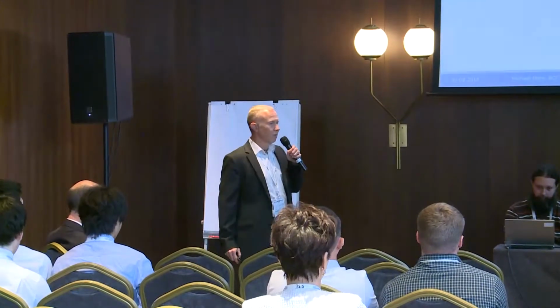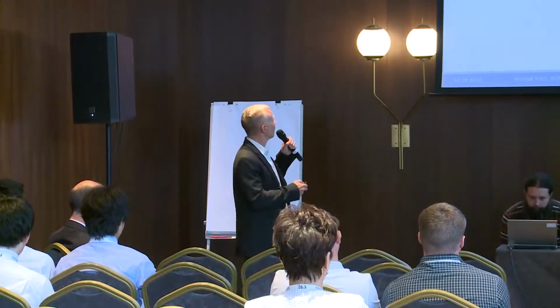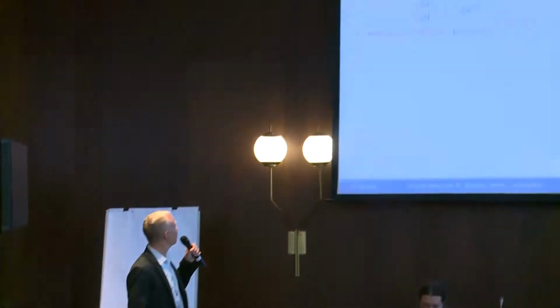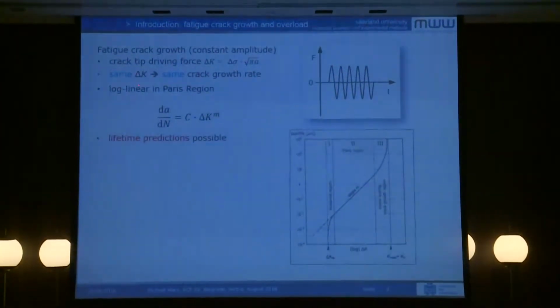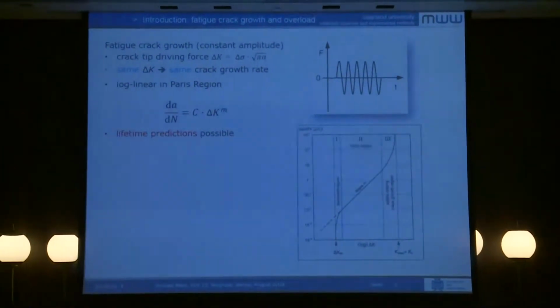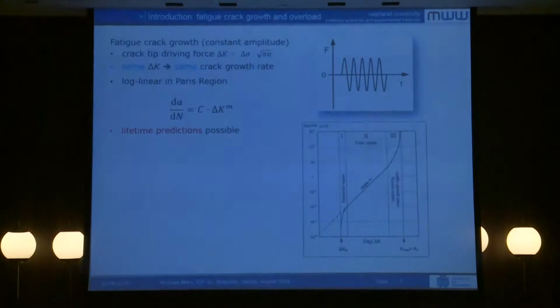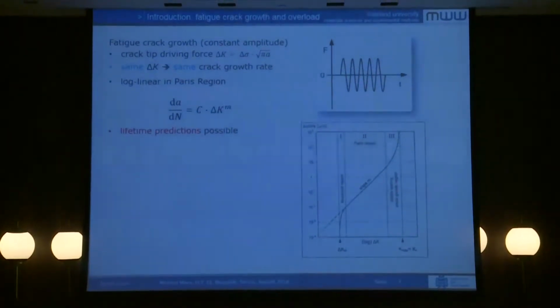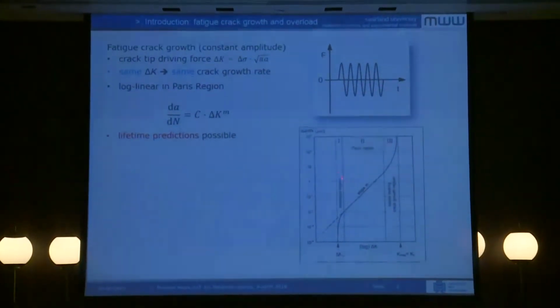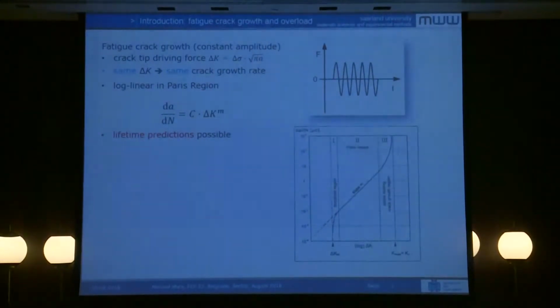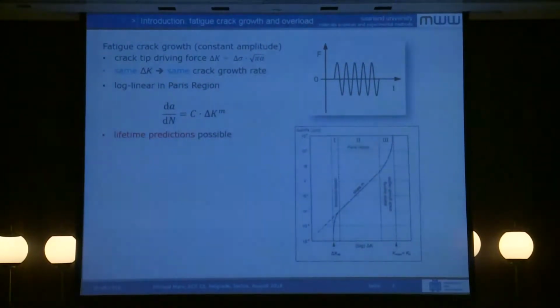So if we typically investigate fatigue crack propagation, we do this with a constant load amplitude, as you can see here. Our driving force then is the cyclic stress intensity factor. Same cyclic stress intensity factor means same crack propagation rate, and then we get our dA over dN diagram. From the Paris regime, then we can calculate our lifetime.